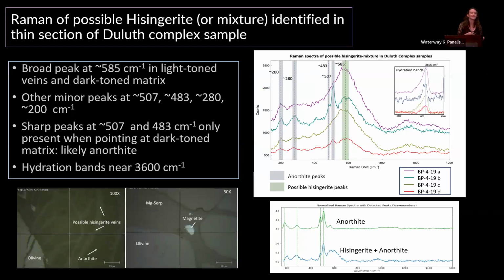But we kept looking, and I started looking at the thin section specifically, and we saw these veins here. And when we pointed the laser at these veins, we saw a band at 585. It was very broad, which was interesting. And sometimes it had these peaks on the shoulder, which I realized to be anorthite, which is very common in these rocks. So we also saw hydration bands at around 3,600, which makes sense since serpentine is a hydrated mineral.